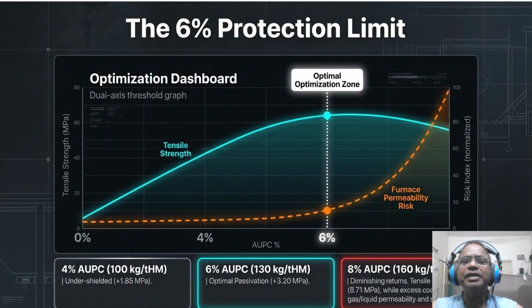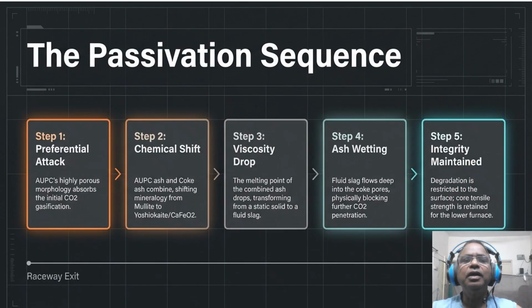So, coming to the passivation sequence. Let's follow a single coke particle as it exits the raceway. Step 1, preferential attack. Step 2 is the chemical shift, step 3 is the viscosity drop, and step 4 is the ash wetting. Step 5 is the integrity maintained. So this is a chronological journey. The AUPC absorbs the first CO2 hit, the mineral shifts, the slag melts and wets the pores, and finally the core tensile strength is retained for the lower furnace. This sequence ensures that the coke stays strong exactly where the mechanical pressure is at its peak.